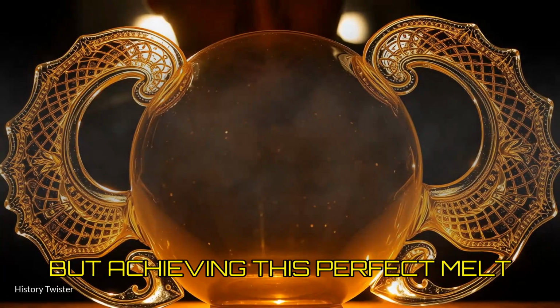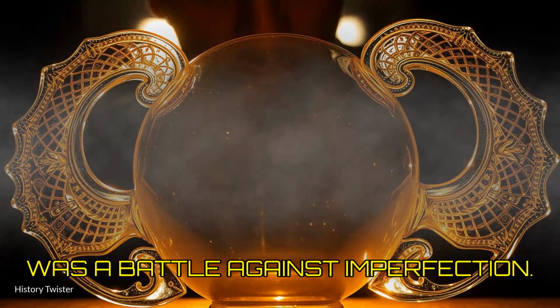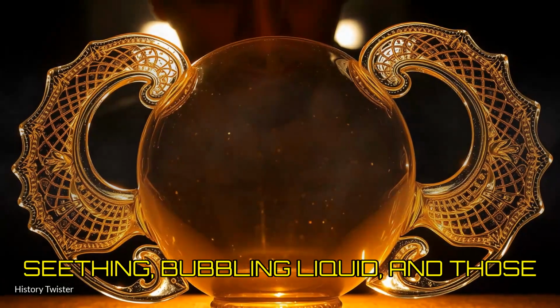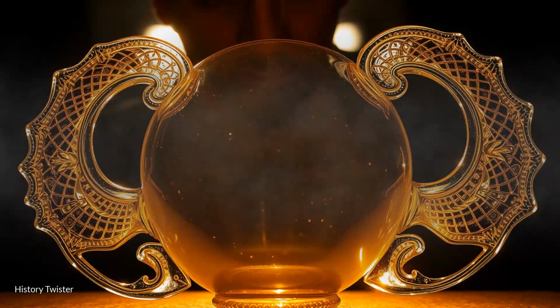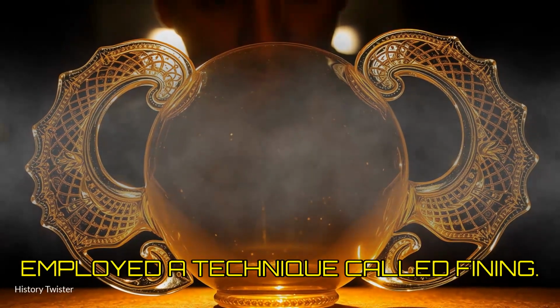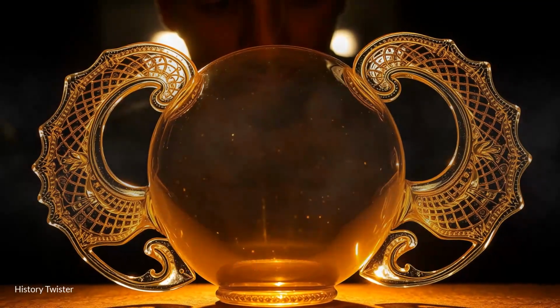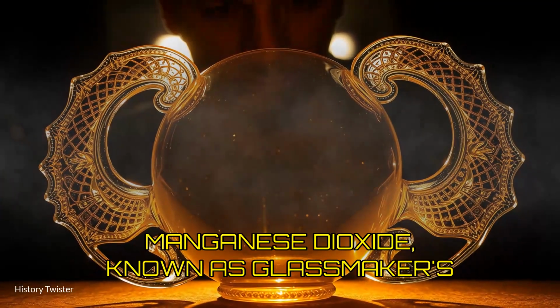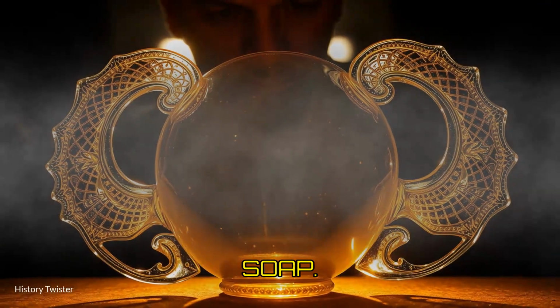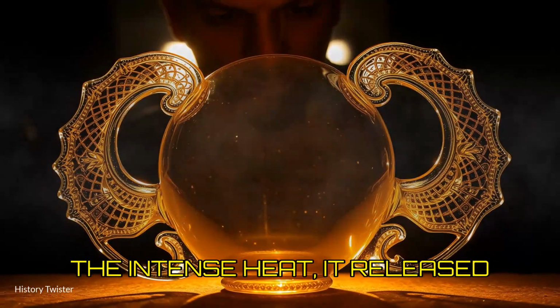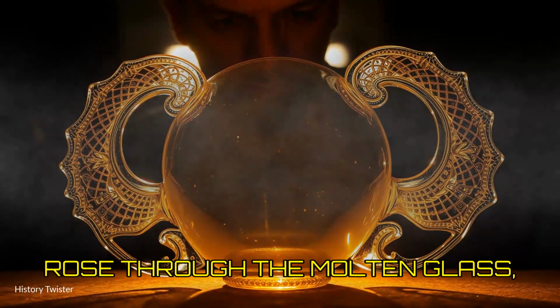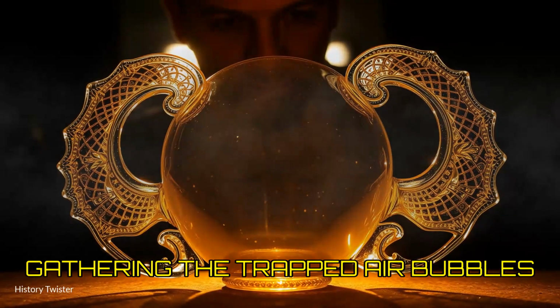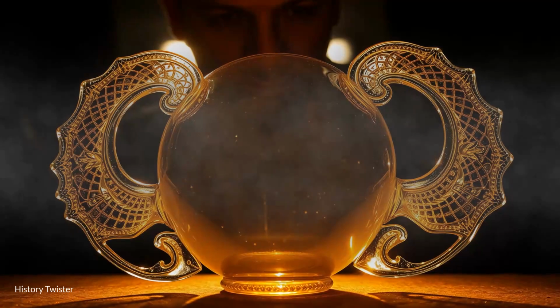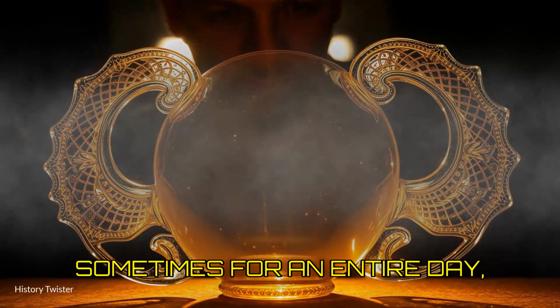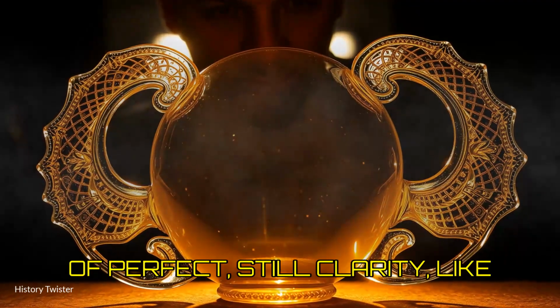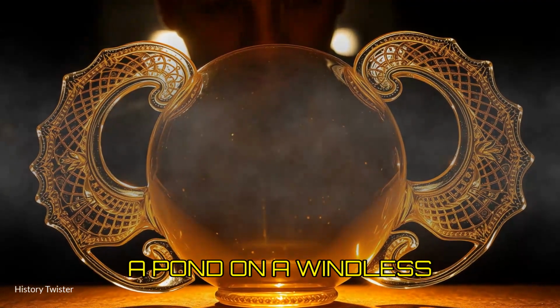The master could take his time, coaxing the glass into forms of breathtaking thinness without it stiffening and shattering on the iron rod. But achieving this perfect melt was a battle against imperfection. The molten cristallo was a seething, bubbling liquid, and those bubbles were the enemy. To remove them, the master employed a technique called fining. He would add a special clearing agent to the batch, often a small piece of manganese dioxide, known as glassmakers' soap. As this additive decomposed in the intense heat, it released tiny streams of oxygen that rose through the molten glass, gathering the trapped air bubbles and carrying them to the surface to pop. The melt would then be left to simmer and settle, sometimes for an entire day, until it achieved a state of perfect, still clarity, like a pond on a windless morning.